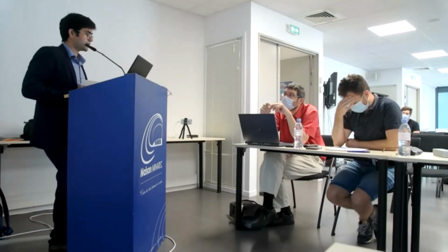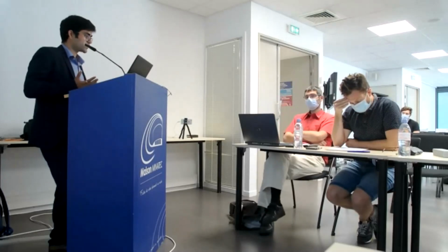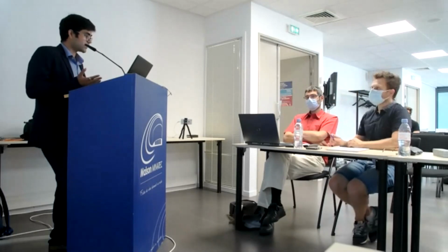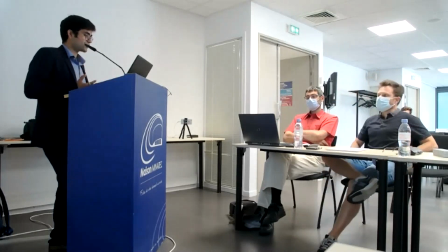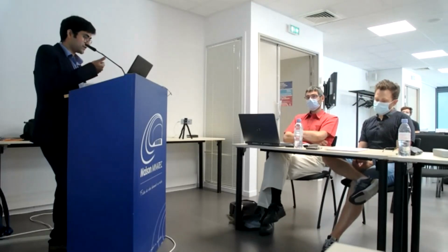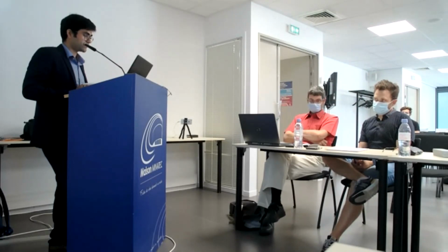Yeah, in fact, I meant this because most of the pressure drops reported in literature are specifically applied to welding conditions. And in welding conditions, you have way lower thermal gradients, and even the strain rates are quite low compared to what we have found. For example, the strain rates mostly reported in literature are like 10⁻⁵ per second. And here we came up with an empirical solution to estimate a strain rate which is several orders of magnitude higher than the strain rates in welding conditions. So based on these points, the thermal gradients and the strain rates which we have estimated specifically for L-PBF, the pressure drop goes so high in value.